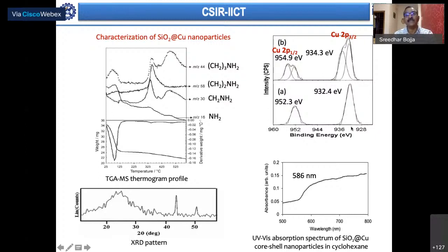But after a few reactions, the reused catalyst was analyzed, and we observed two peaks—along with copper in metallic form, there is another peak due to copper 2+, meaning some of the copper nanoparticles have changed to copper 2+. That is the reason you see these two peaks, one due to copper and one due to copper 2+. So this is how we can know about the element and its oxidation state by XPS.